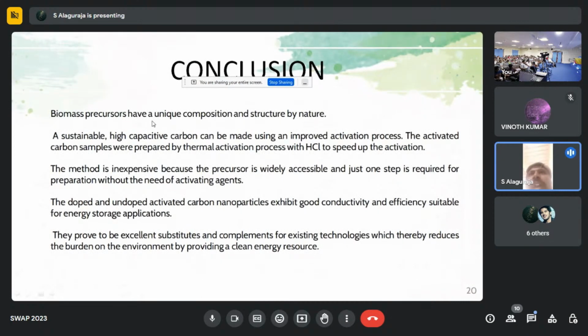Conclusions. Biomass has a unique composition and structure by nature. A sustainable high-capacity carbon can be made using an improved activation process. The activated carbon samples were prepared by a thermal activation process with hydrochloric acid to speed up the activation. This method is inexpensive because the precursor is widely accessible and just one step is required for the preparation, without need of activating agents. The doped and undoped carbon nanoparticles exhibit good conductivity and efficiency suitable for energy storage applications.